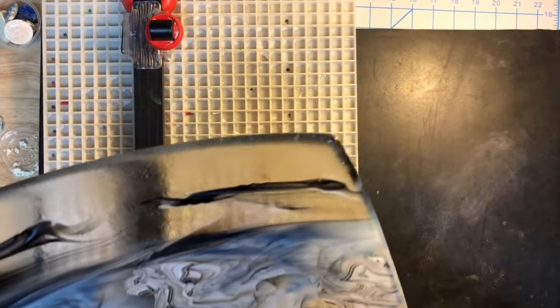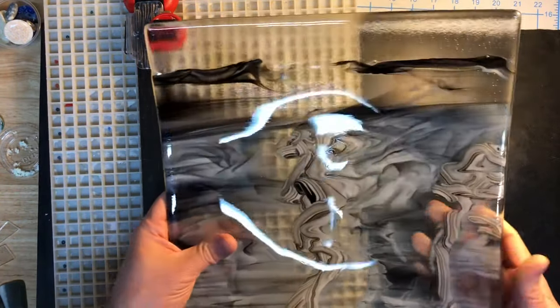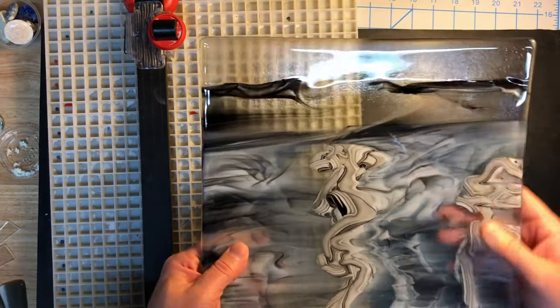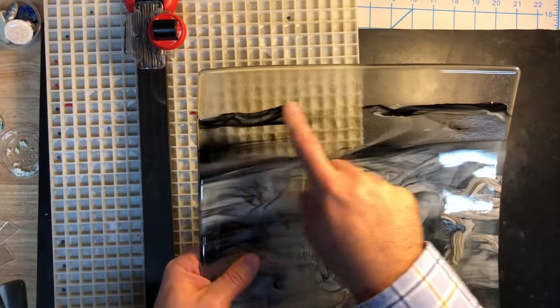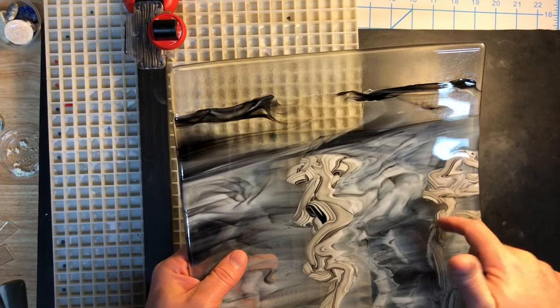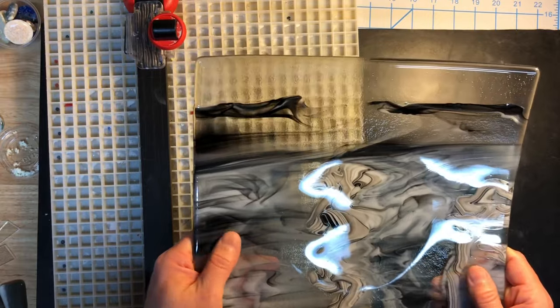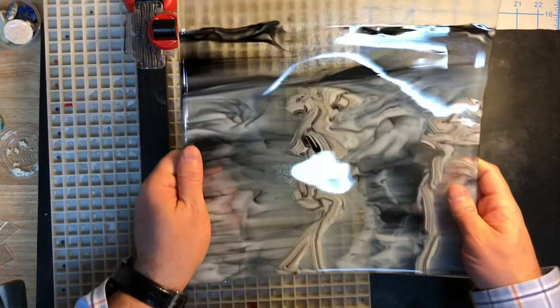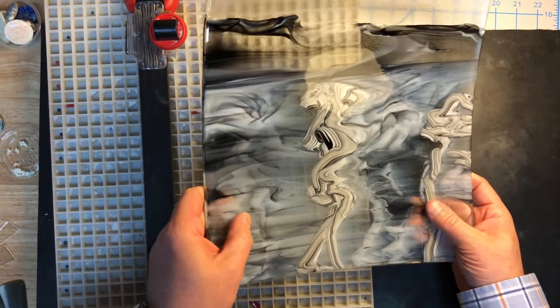That turned out exactly as I had hoped. Here's the finished piece — it worked perfectly. I love the way it slumped into the mold. I love these square slumpers from Bullseye, so I followed their firing schedule: 300 up to 1180, held for five minutes, and then a standard anneal down, and it turned out really well. This is not the only platter you'll find with rolled edges. Bullseye had a video that they featured — I'll drop the link into the description below. I am naming this piece Zeus because I think it totally looks like a face.